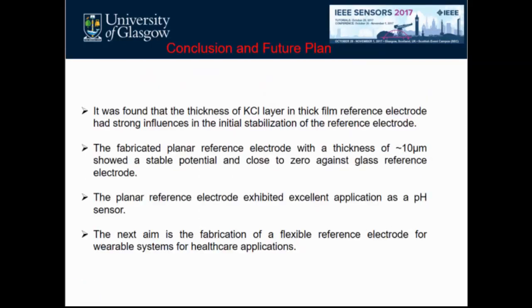Conclusion. The reference electrode with a 10 micrometer thickness layer shows a very good stable potential against the glass reference electrode, and the sensitivity shows 55 millivolt per pH for a pH sensor.